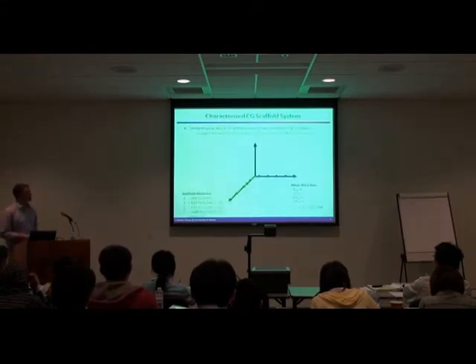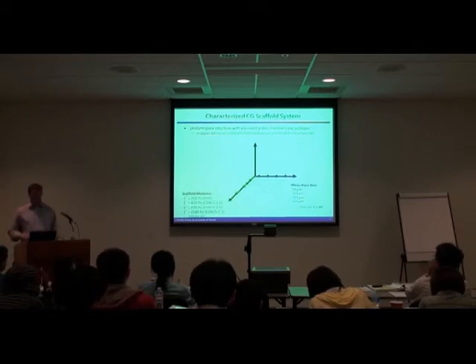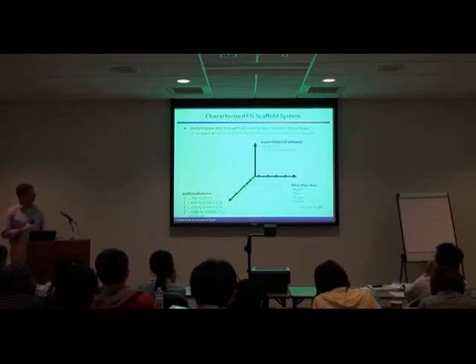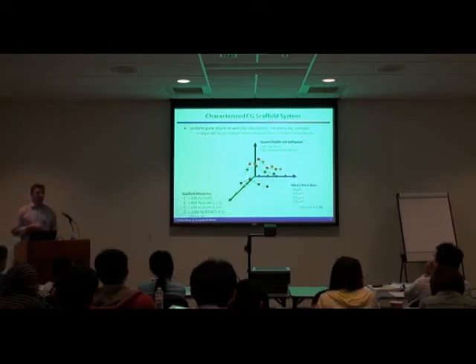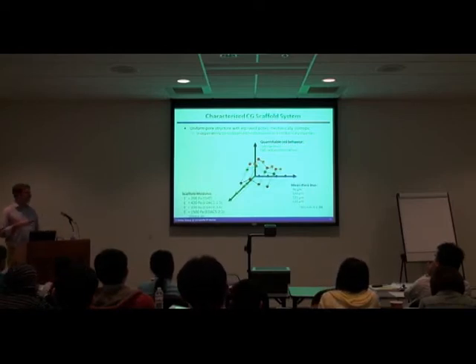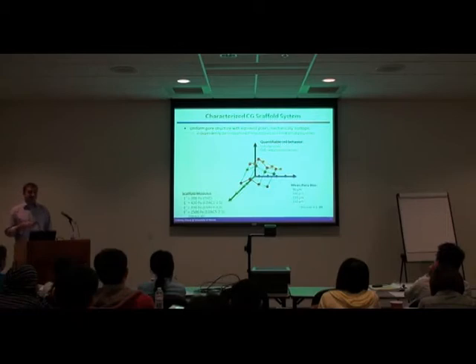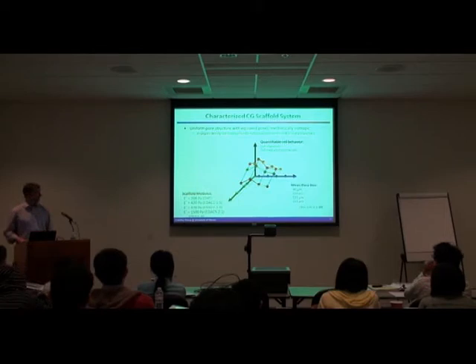So what we had now is a system that we had built where we could affect scaffold modulus and the mean pore size of our scaffold independently of one another. We thought this might be a really neat tool and a neat model system to look at similar types of behaviors that Yu-Li Wang's group and a number of other groups looked at before, to try to get an understanding of features such as cell migration and cell-mediated contraction, and whether there is a complex relationship between pore size, microstructure and mechanical properties that you don't necessarily get out of a 2D membrane system.